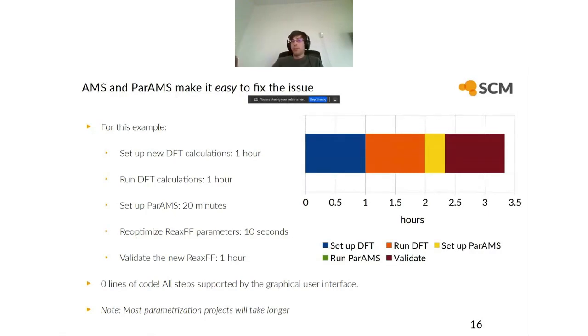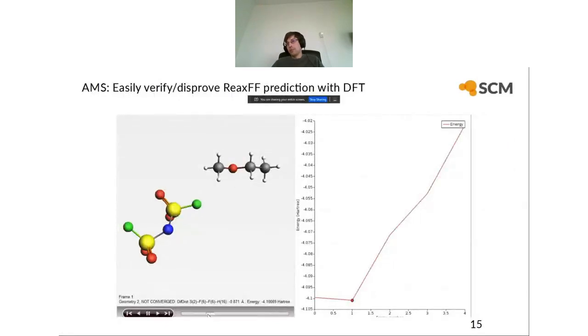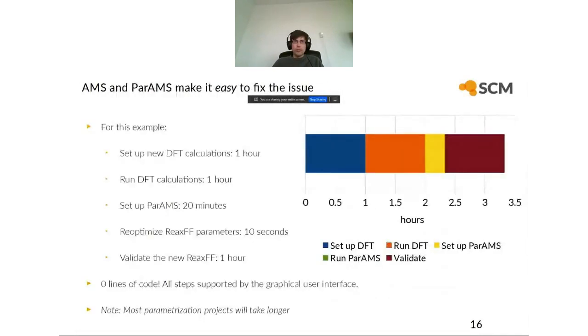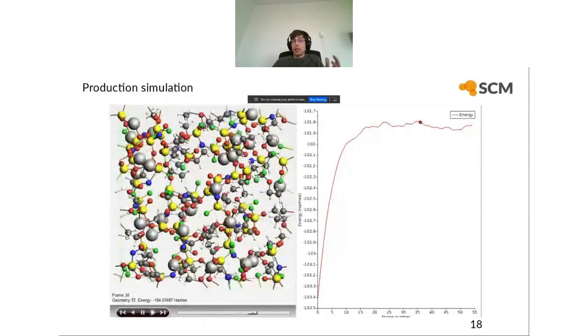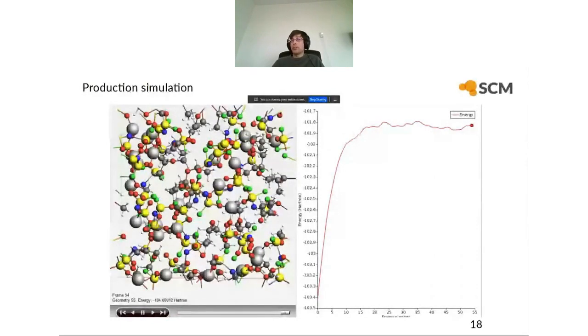After fitting the new force field, the energy-versus-dissociation curve now goes up in roughly the same way as DFT — this is my re-optimized version of the force field compared to the DFT curve, which is close enough. With this new force field you can use it in production simulations — for example, a full system with lithium ions, anions, and solvent, where you can calculate the diffusion coefficient which relates to conductivity. The summary is that you can use PARAMS very easily and efficiently together with the Amsterdam Modeling Suite for DFT calculations to refit force fields.